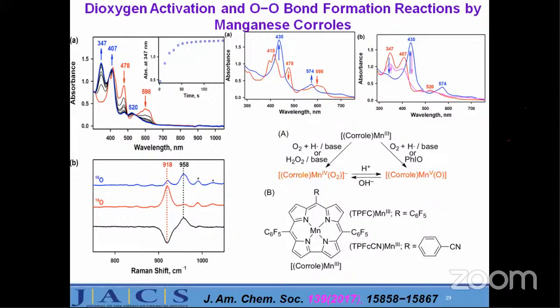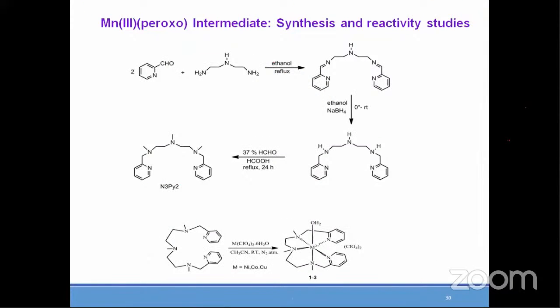Now, that was some work done in Nam's lab. Again, I am coming back to the work done in our laboratory. Very recently, we prepared a pentadentate non-heme ligand. You can see here, it is similar to N4Py. This ligand was prepared by a simple reaction. You can take a diamine and condense it with pyridine carboxaldehyde, reflux it, and then you get this. Then you do hydrogenation and methylate it. So this ligand was prepared, and then we thought of making the manganese compound of it.